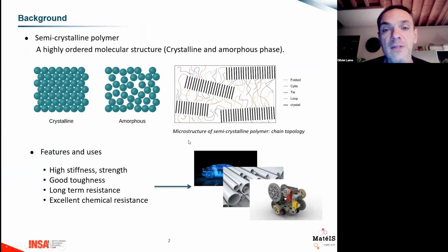Okay, so here is the general microstructure of a semicrystalline polymer, which is in between amorphous and crystalline. We have crystalline lamellae, and in between we have an amorphous phase, which is very complicated. The mechanical properties of the polymer are given by the crystalline lamellae, which give essentially the stiffness and also the yield properties. But the long-term properties are given essentially by the amorphous phase.